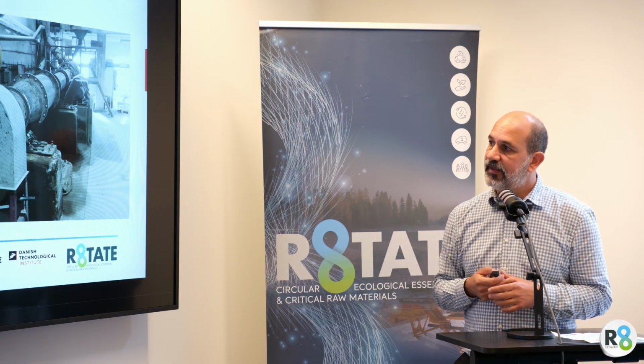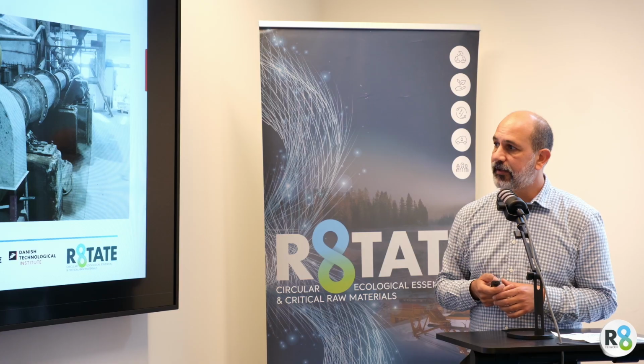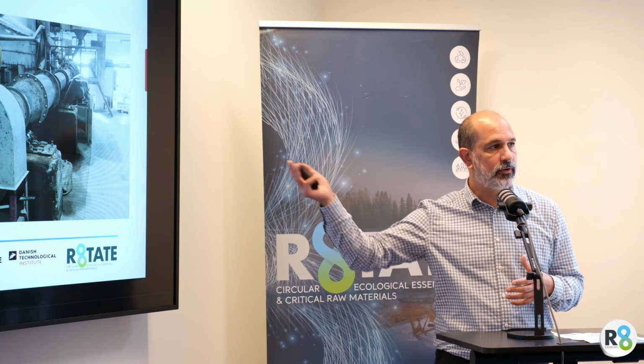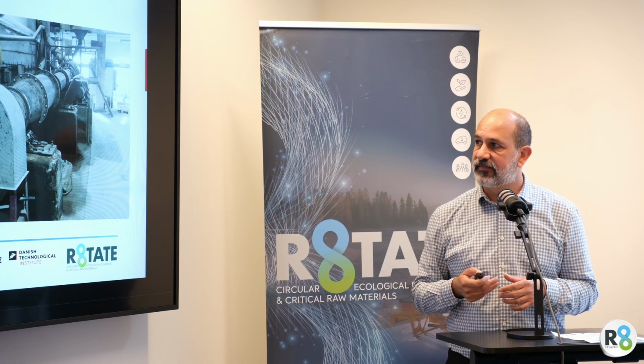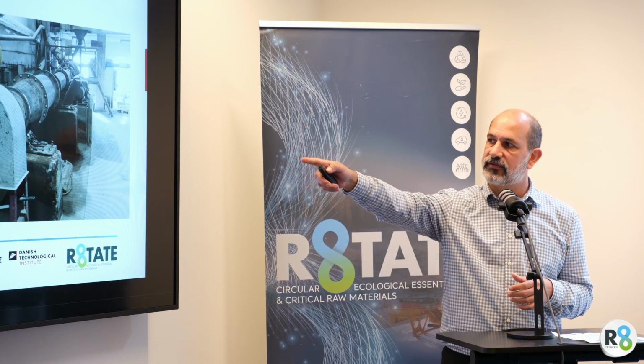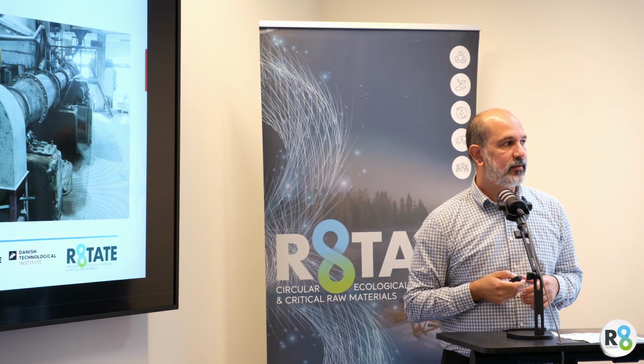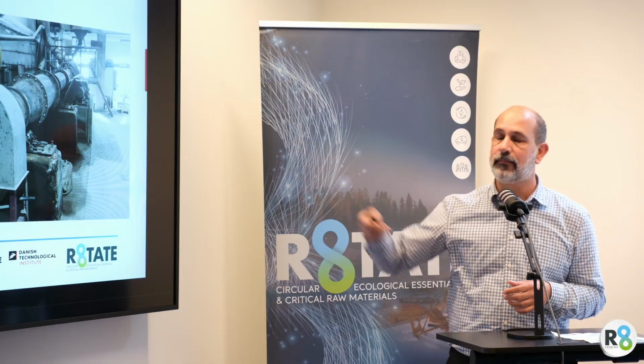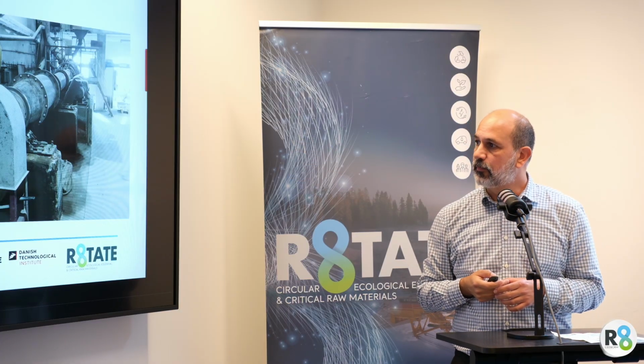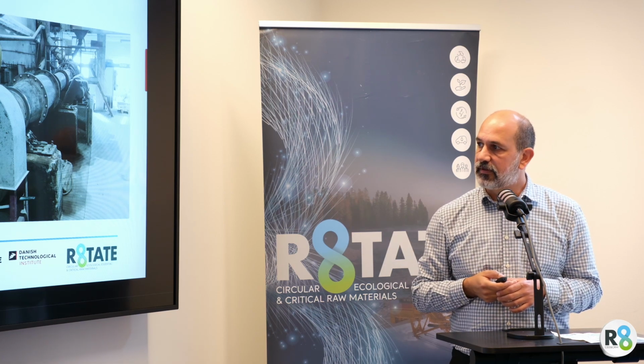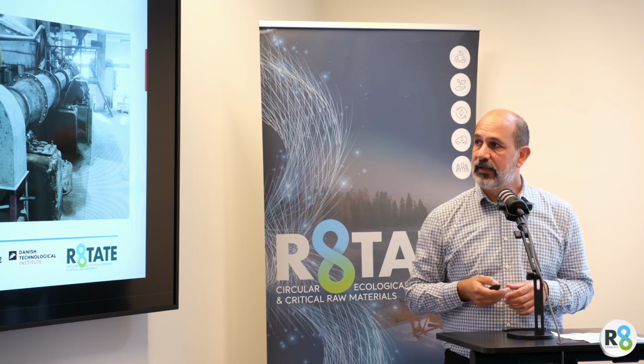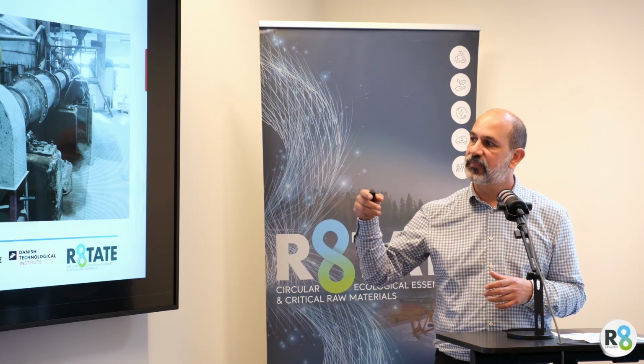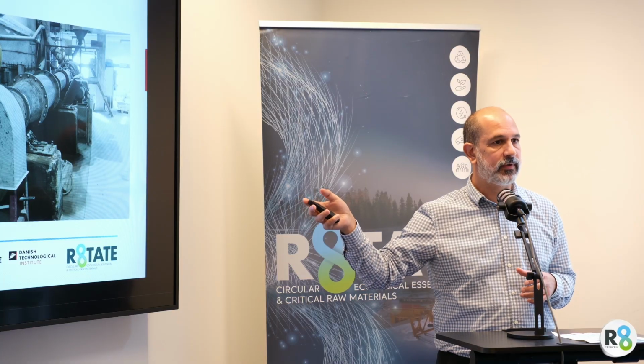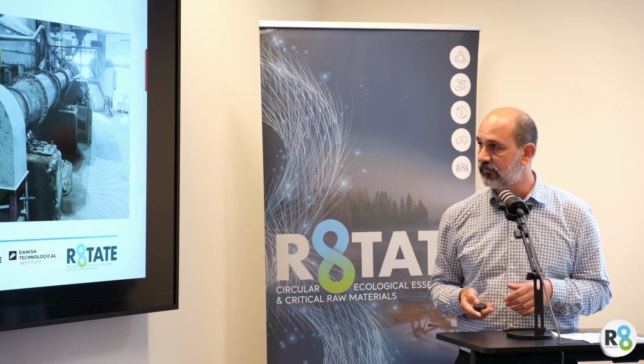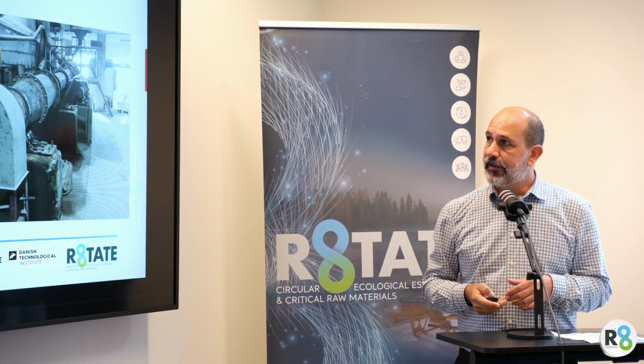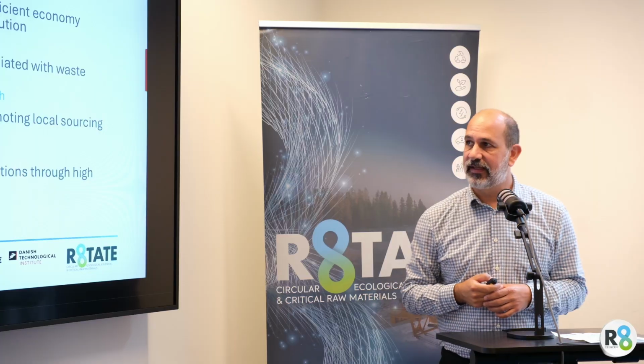So with these recipes, we went to Poland. So with the subcontractor, we produced 1 ton of these sludge-based lightweight aggregates. Here you can see some pictures how we went from the small rotary kiln that we have in our lab to this big rotary kiln that we use in Poland, and there you have some pictures of the calcination ongoing there. At the moment, we are busy with testing the performance of these lightweight aggregates in screed mixes that we are producing at the moment at Vito. So this is a bit the end of the story.